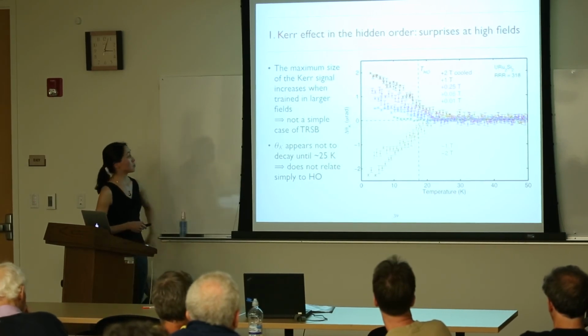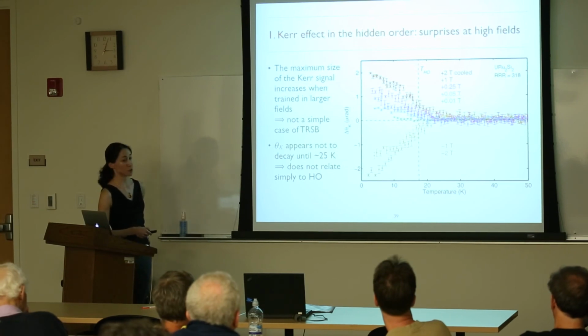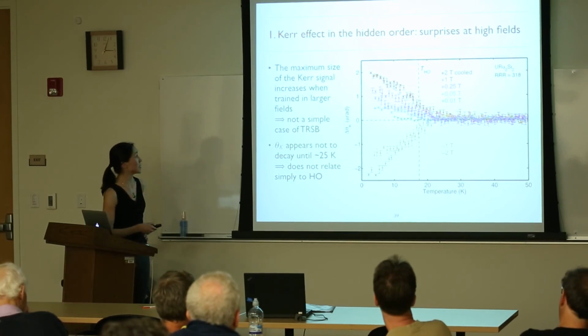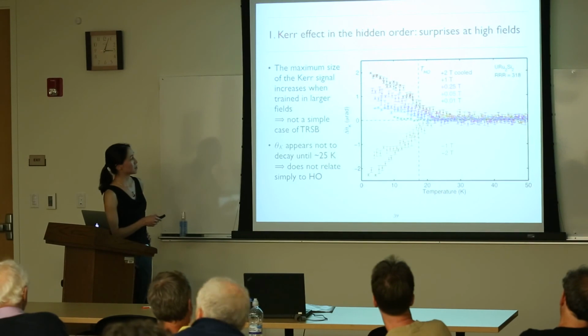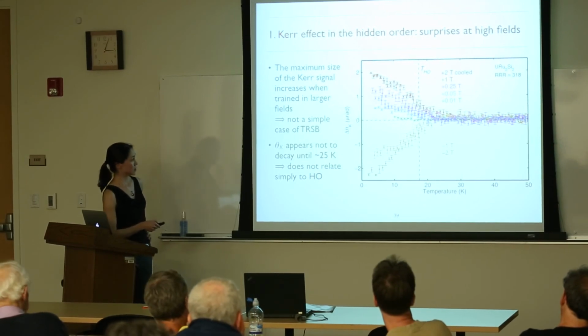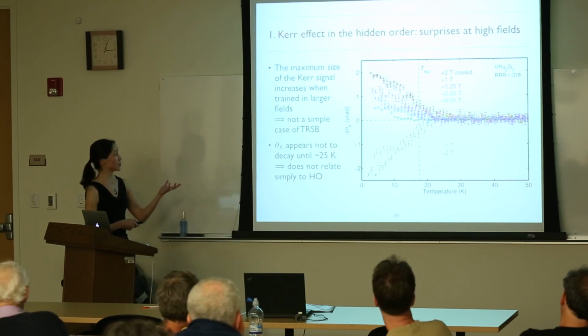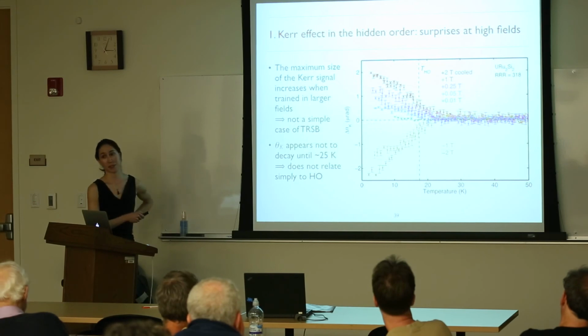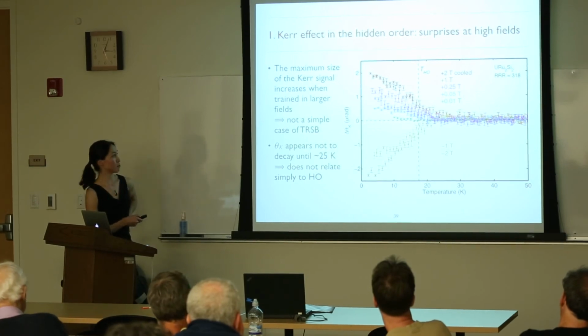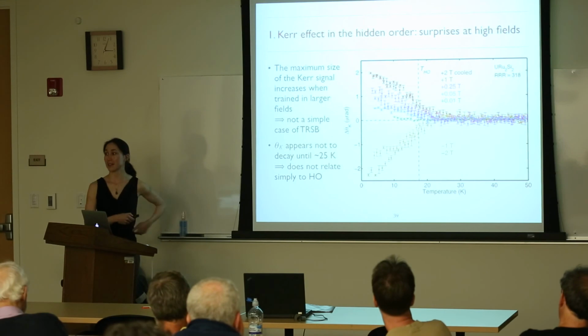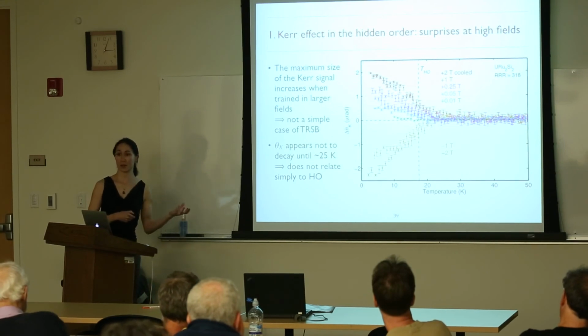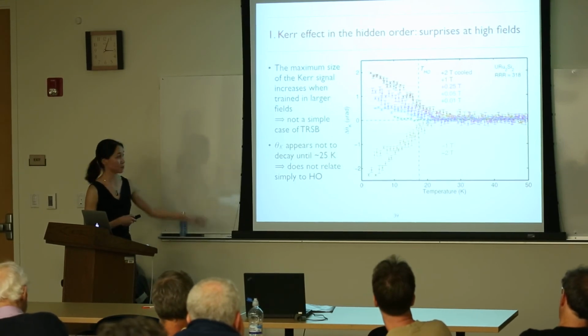Another thing that we tried to do, since we're dealing with a high temperature phase and we don't have to worry about vortices and the like, is cooling down the material in larger and larger fields. So this is at 2 Tesla going down to 100 Gauss, and then -1 or -2 Tesla. There are a few things that are striking about this. The first is that the size of the Kerr signal seems to depend on the size of the field that you use to train it, which is certainly not what you would expect, at least in our very simple picture of time reversal symmetry breaking states that we look at with this kind of technique.